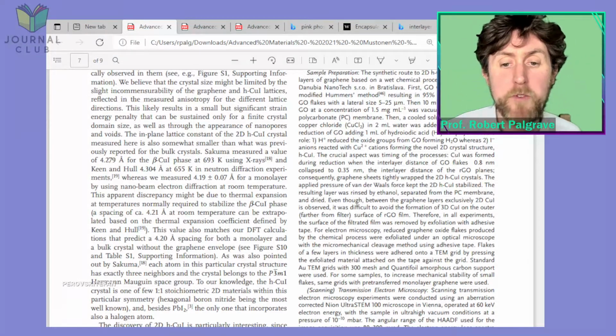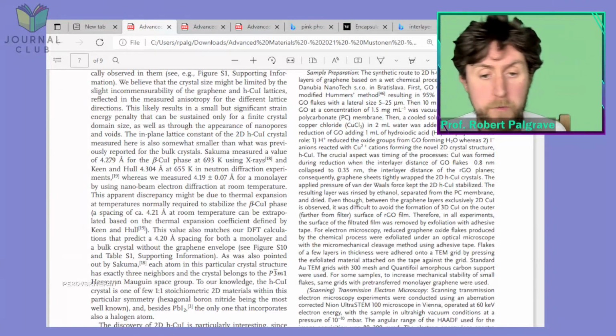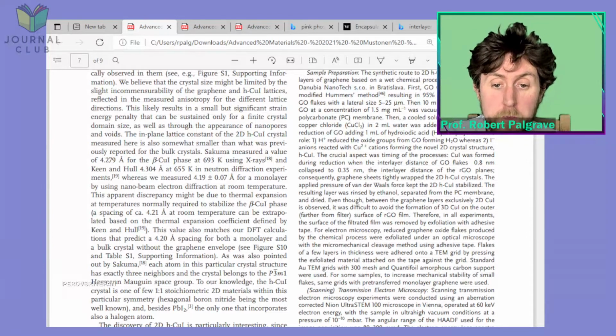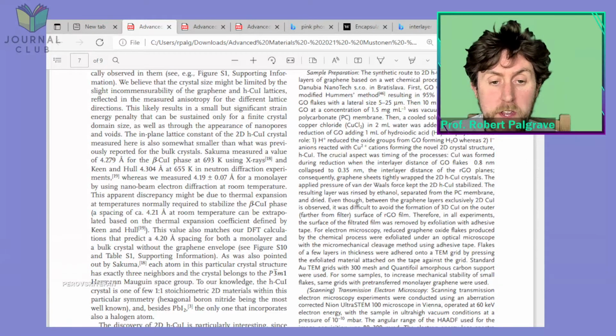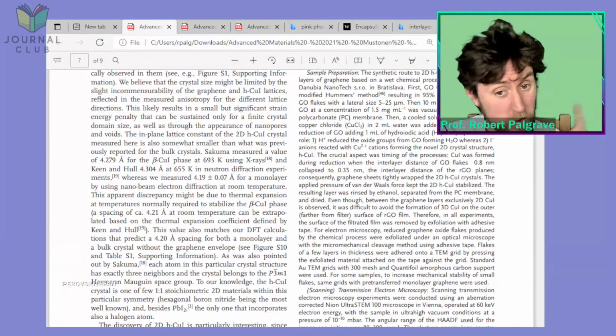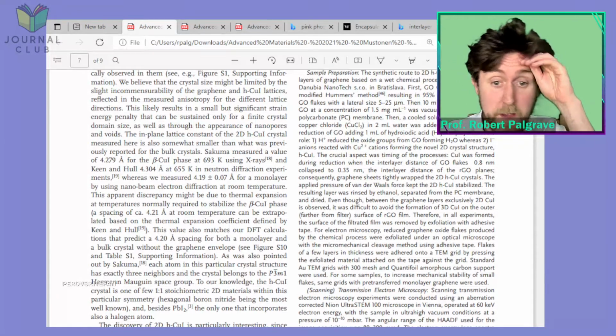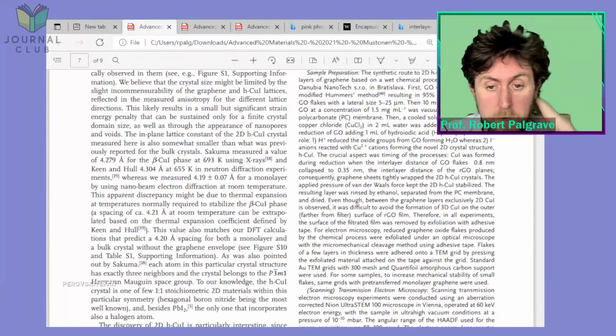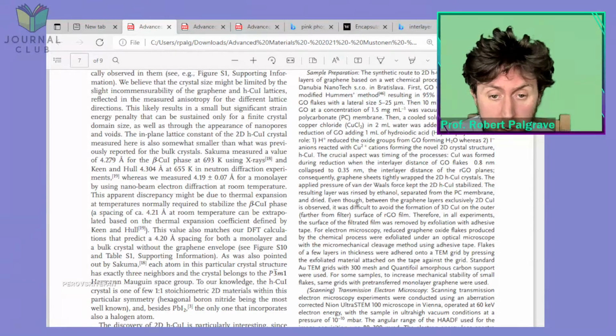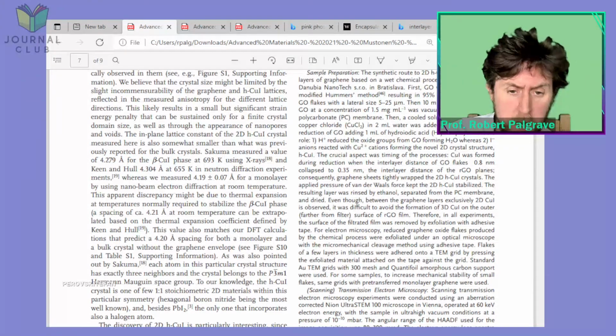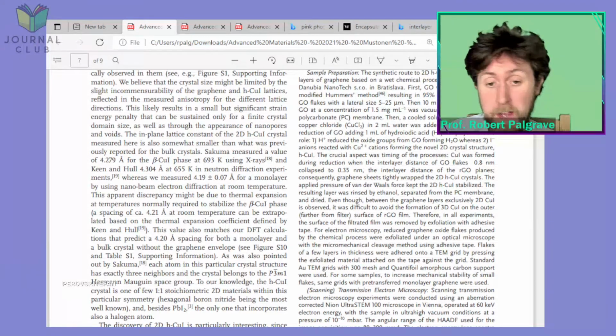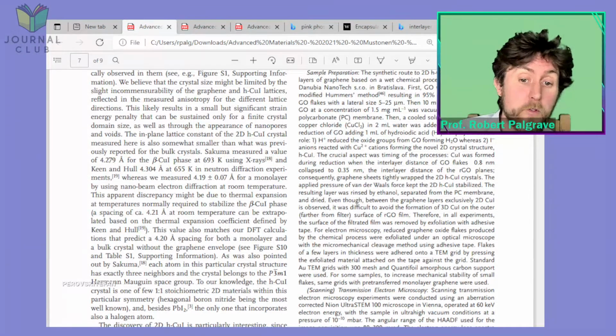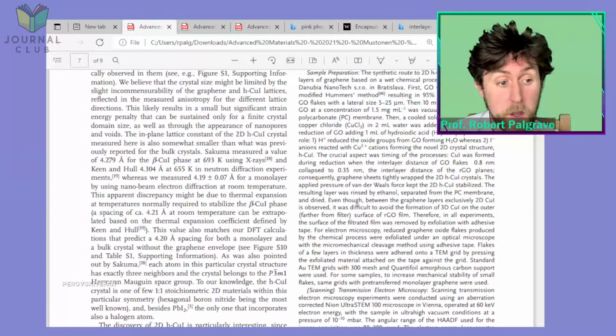Rinsed in ethanol, separated from the PC membrane, polycarbonate membrane, and dried. Even though between the graphene layers exclusively 2D cuprous iodide is observed, and we saw that in figure 1 earlier on, we'll go back to it in a second, it was difficult to avoid the formation of 3D cuprous iodide on the outer surface, farther from the filter, of the reduced graphene oxide film. Okay, it's on the top, and probably in other places in the reaction you're going to get the 3D form of cuprous iodide, the cubic form of cuprous iodide.